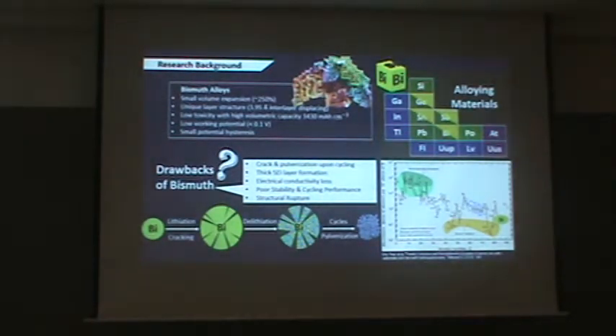Bismuth is one of the alloying materials that is very appealing because it has a small volume expansion compared to other alloying materials and also a high volumetric capacity. But like other alloying materials, it tends to expand, causing cracks and pulverization upon lithiation and delithiation. The usual way to solve this is by using a coating material, either carbon or SiOC.